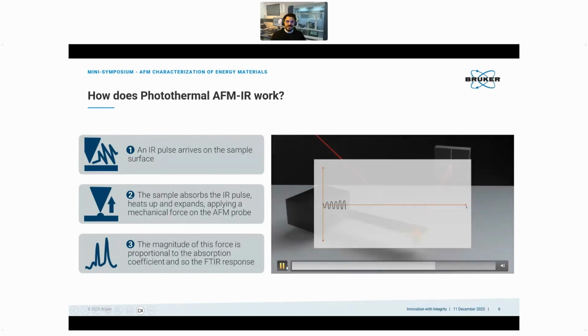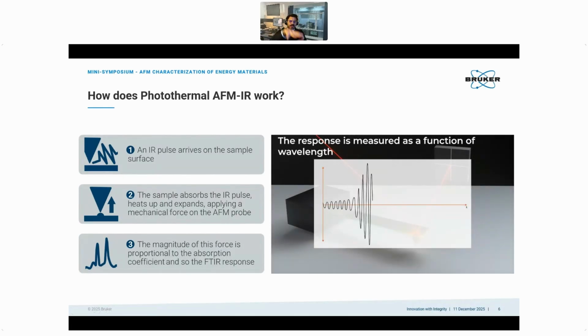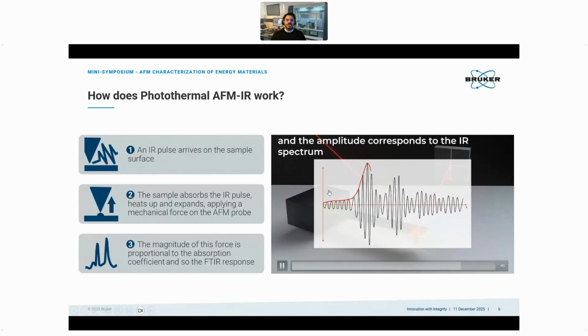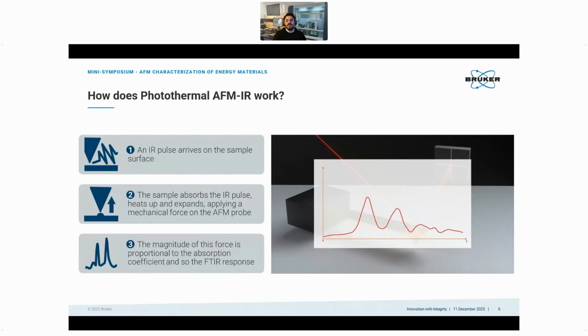So we will be measuring this, and if the amplitude of this expansion changes due to the absorbent properties, the amplitude of the cantilever vibrations will change, and that's how we reproduce basically the spectra, due to the change of how much the sample has expanded, so how much it has absorbed the infrared light. So hopefully this clarifies for those who haven't seen it before, or maybe was not clear for them, how actually we measure it. So basically we measure with the probe the change of the surface due to the infrared absorption.